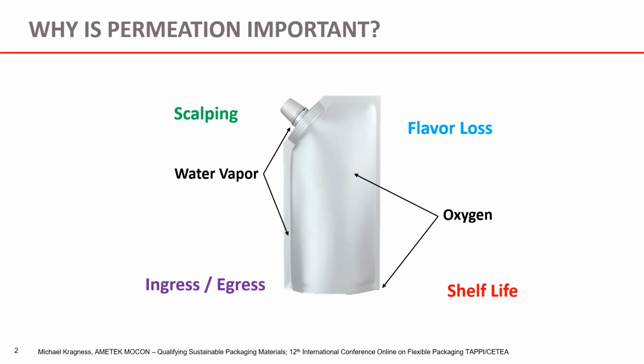Now, when I look at a package, I like to look at the package as a system consisting of different components. So all of these components, from the interface of the closure to the pouch, to the seams, to the gusset, they all have to be working properly, because they could all be potential permeation leak points. So now, of course, you're going to get water vapor and oxygen in the atmosphere. But say this is a flavored drink. So you may get some flavor loss in a process known as scalping, to where that flavor compound actually can be absorbed within the polymer that was used to seal the seams, or to convert this base material into this pouch. So you always have a lot of things going on.